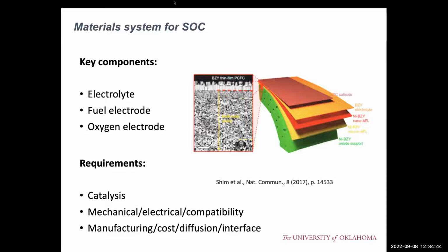perovskite materials. And then we dope some transition metal into the materials to form oxygen vacancies, and that can facilitate the transport of the proton. But for each layer, I want to give you some very simple introduction. For the electrolyte, it has to be a very dense layer. So the hydrogen at one side and oxygen at the other side cannot penetrate through this electrolyte membrane. So we need to fabricate a ceramic dense layer in the middle.